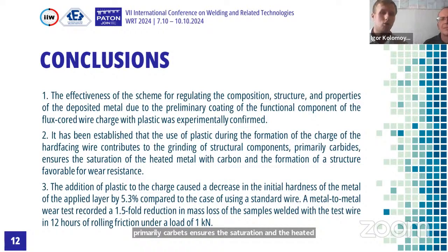The addition of plastic to the charge also caused a decrease in the initial hardness of the applied metal by 5.3% compared to the case of using a standard wire. A metal-to-metal wear test recorded a 1.5-fold reduction of mass loss of the samples hard-faced with the test wire in 12 hours of rolling friction under a load of 1 kilonewton.